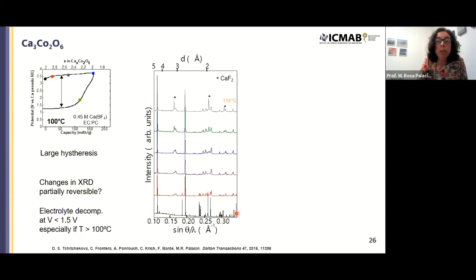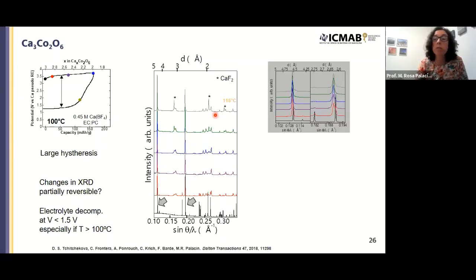This is the pristine compound. Then when we start oxidizing, some regions of the pattern really change a lot. And here at the end of oxidation, we have a new phase, which seems to be pure. But then when we try to reduce, nothing really seems to happen except for the increase of this peak, which corresponds to calcium fluoride, which is due to the decomposition of the electrolyte, and especially if we go to higher temperature. So first question: are those changes related to the extraction of calcium?